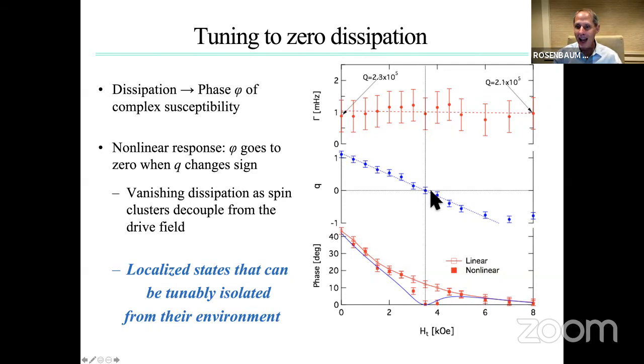Okay, so the fact that you're decoupling from the world, that these are localized states that can be tunably isolated from their environment, is borne out by the measurements of the global susceptibility. So the hope, of course, is that one can tune these spin clusters, which are now labeled by frequencies, to decouple from their environment and then excite a multitude of spin clusters of different frequencies and then mix them, which would be the computation. We've not done that yet.